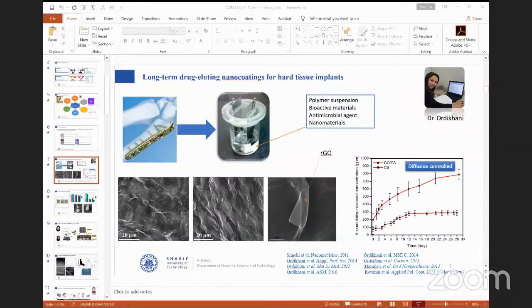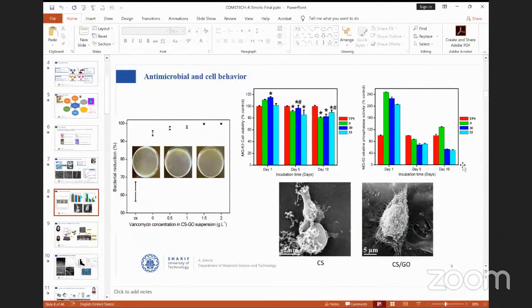The result was very interesting, as you see in this figure, in the right downside, if it is visible. The lower curve shows the release of the drug. As you see, after 12 days, it's almost finished. But the upper curve shows the incorporation of vancomycin conjugated to the graphene oxide. We could load in more drug and release it for a longer time, which is very helpful for practical application. I turn to slide 8, if it's visible.